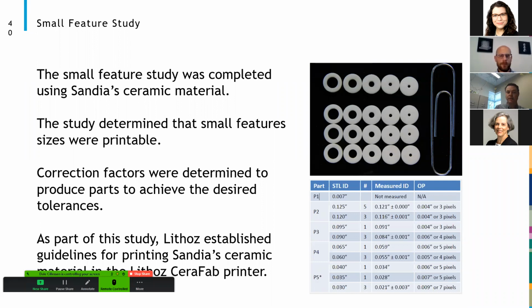You can see that we are achieving diameters all the way down to 20 thousandths of an inch, up to approximately an eighth of an inch, and a slight misalignment as far as tolerance, but this can be adjusted. And we did learn a lot during this process about establishing guidelines for future printing of this component. This also was done using our base ceramic material.